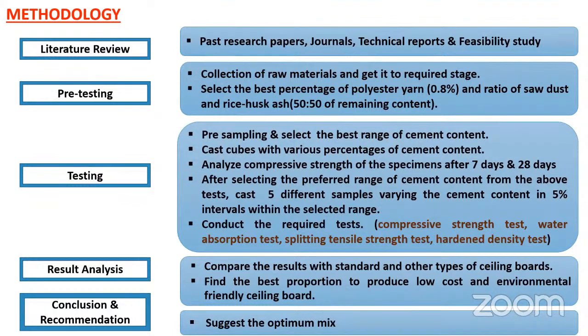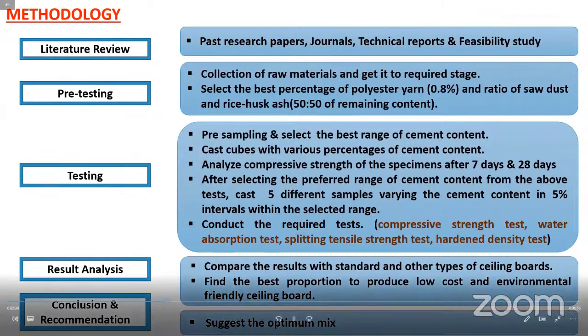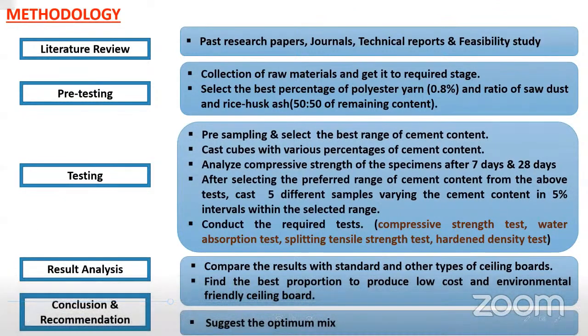Then select the best percentage of polyester yarn as 0.8%, and the ratio of sawdust and rice husk ash as 50% of the remaining content, based on previous research conducted on the selected materials to produce similar products.